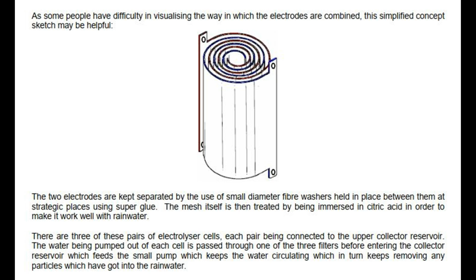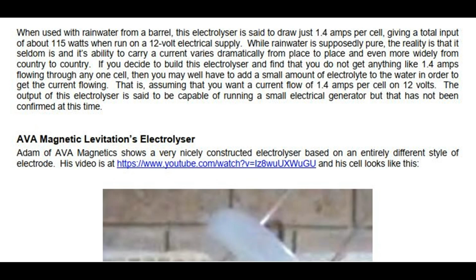The mesh itself is then treated by being immersed in citric acid in order to make it work well with rainwater. There are 3 of these pairs of electrolyser cells, each pair being connected to the upper collector reservoir. The water being pumped out of each cell is passed through one of the 3 filters before entering the collector reservoir, which feeds the small pump which keeps the water circulating, which in turn keeps removing any particles which have got into the rainwater. When used with rainwater from a barrel, this electrolyser is said to draw just 1.4 amps per cell, giving a total input of about 115 watts when run on a 12-volt electrical supply.